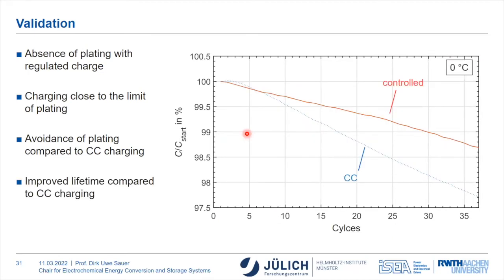Now the question is, does it have an impact on the battery? And even though these are just 35 cycles, we can see that if we go with a constant current charging, so without control by our algorithms on the battery management system, we have a capacity decrease following this dotted line here. A test has been done at 0°C. And if we control the voltage according to what I just have shown, the aging is significantly lower because we can avoid the plating. And not shown here, still we were faster in recharging the battery in the controlled way, and we saved lifetime.